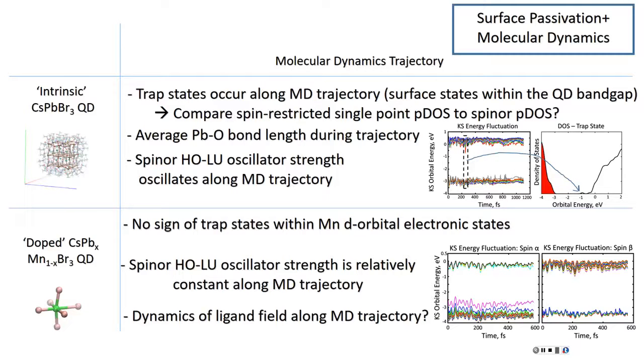Again, if you're looking at your spectra, it looks like you excited the very first peak or the second peak, which is more intensive. Second and third. If we're looking at relaxation, that looks like it's deep enough that you really go into the high excited state. Second, I would say intermediate, because your first one probably goes from just the HOMO.